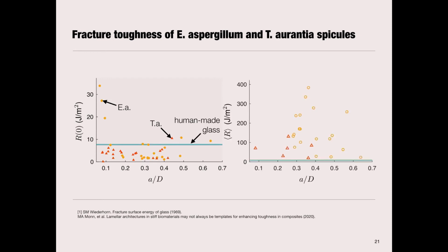And same thing, getting work of fracture for the monolithic spicules was actually quite a bit harder because when we're computing work of fracture, we need to have a continuous force displacement response indicating that there's no unsteady crack growth and unaccounted for kinetic energy when we're doing that incremental energy balance of external work versus elastic energy and energy dissipated by fracture. So there's far fewer samples here. But we see that they do have a lower average R value as well.